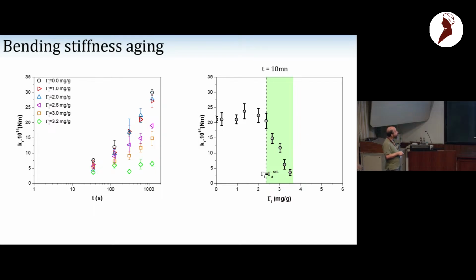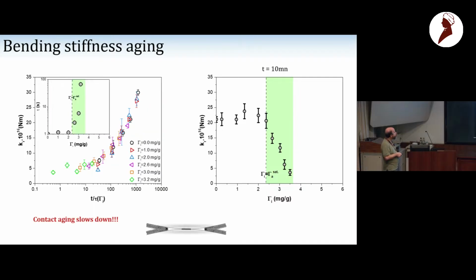The contacts at low dosage, you find, you still form contacts. But the time-dependent modulus depends on the dosage. And it turns out that we can understand that by basically the fact that the polymer changes the reaction kinetics of what's happening in the contact. So basically, we see that we have a stiffness of the contact that depends on time, with a time scale which depends on the reaction. So the picture we have is that the presence of the polymer might slow down the reaction kinetics. We do not know what this reaction is, but it can be slowed down by the presence of polymers.